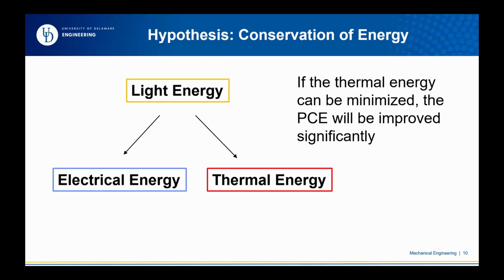So that translates to thermal energy. And if you try to decrease the thermal energy part, that can probably increase the electrical energy part. That is the electricity. People try to use a solar cell to generate electricity. Okay, so this is the ideal case. But people tried the temperature regulation method, trying to decrease the temperature, because the thermal energy decreases and the electricity increases. But when people went down to maybe just 150 Kelvin to 200 Kelvin, they stopped, just because the efficiency did not increase but totally decreased.